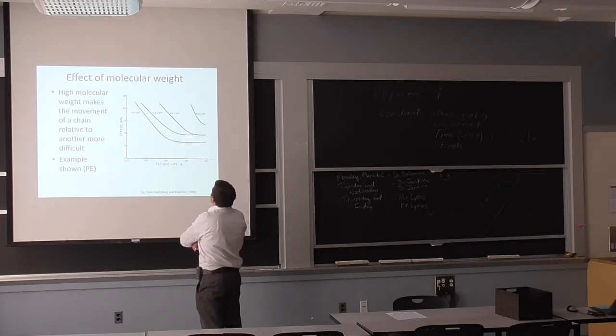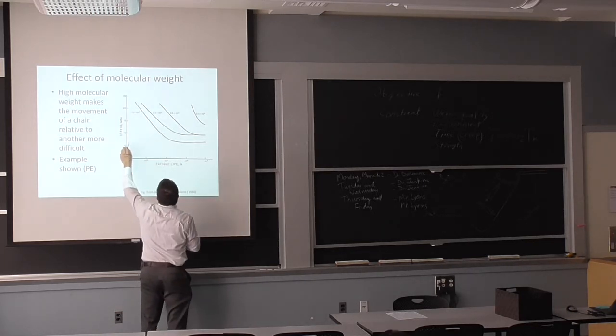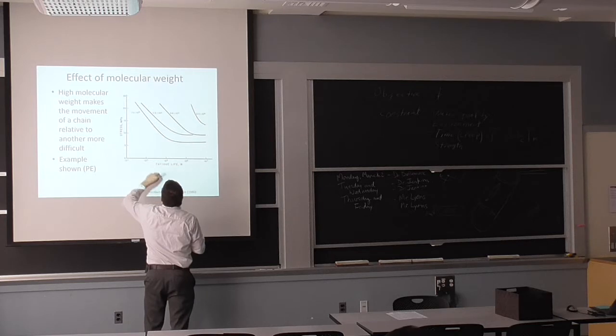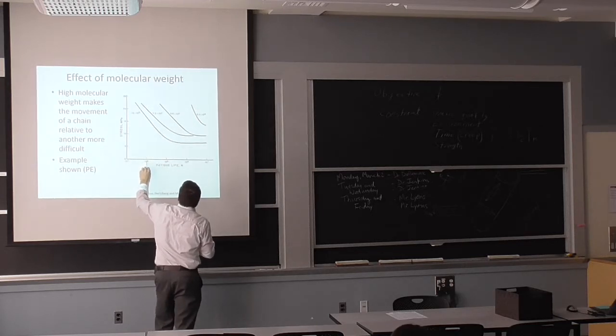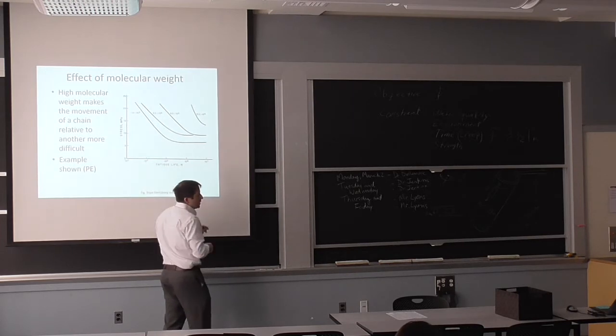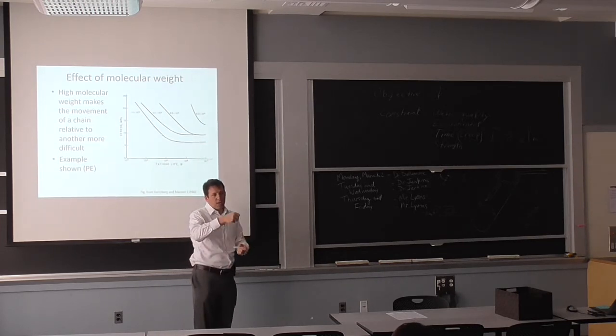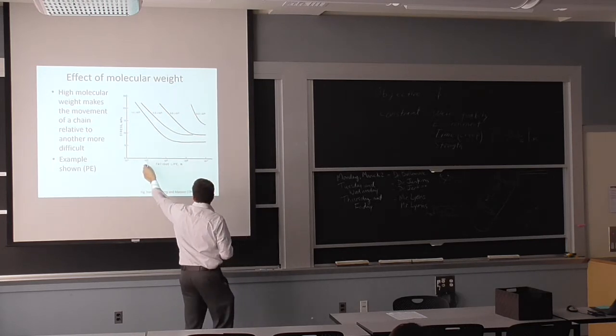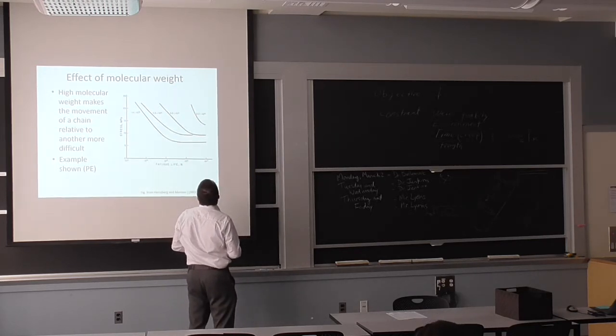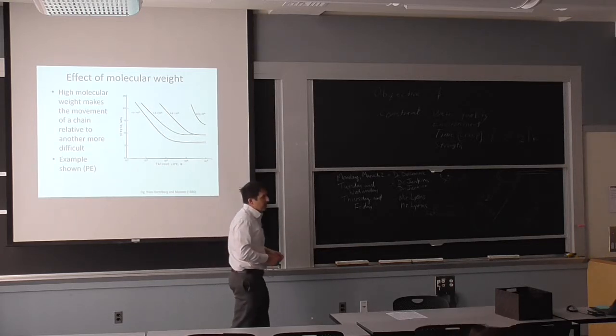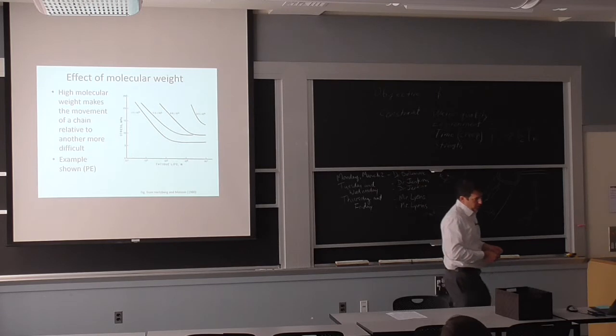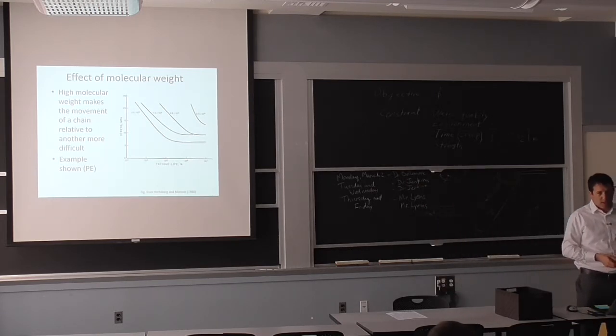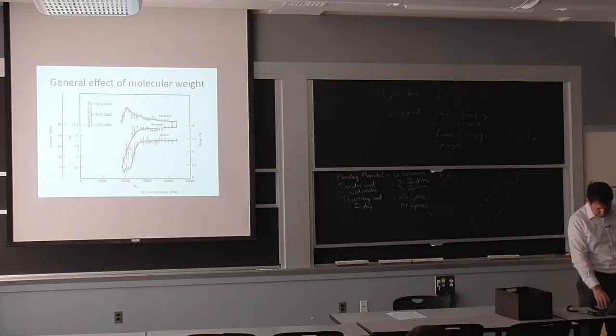We're talking about a weight variation of 1 order of magnitude here. And if, say, we have a stress of 15 megapascal, just for our example, we're switching from 10 to the 4 cycles to failure. This is fatigue. We use fatigue a lot, cyclic loading, to accelerate what will happen under constant load. So you're going from 10 to the 4 to 2 or 3 times 10 to the 6, just by increasing the molecular weight. So that's a real effect, and that's why there's a difference between low density and high density polyethylene. So the high density is the one that has the longer chains.